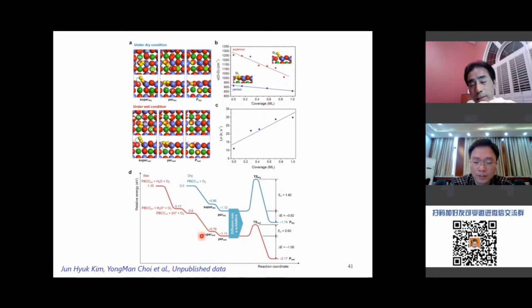So basically you need some catalyst. That's one thing. Another thing, as I explained in one of the slides, is you need a catalyst that specifically promotes oxidation of carbon, like barium oxide. Barium oxide's dissociative adsorption of water creates an OH group. The OH group is going to react with carbon to oxidize carbon. So you need a catalyst that promotes dissociative adsorption of water, creates OH group, and also catalyzes the carbon-OH reaction, producing COH. And then COH dissociates into hydrogen and CO. Now, hydrogen and CO are fuel for SOFC. So hydrogen can be oxidized to water, CO can be oxidized to CO2. So those are the strategies.